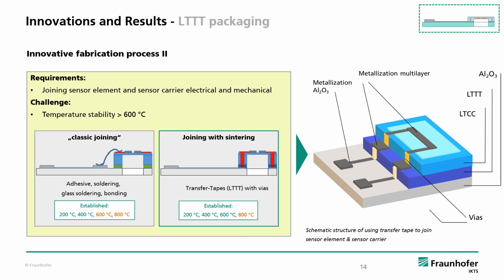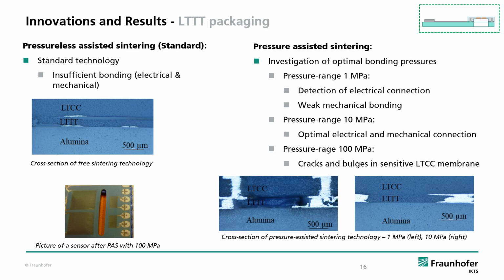The challenge in the LTTT process is finding the optimal sintering parameters. We started with the standard sintering process you can see on the left. Here we had an insufficient bonding, electrical and mechanical, as you can see in the cross-section. The other sintering technology uses a defined pressure while sintering, the so-called pressure-assisted sintering, you can see on the right. First of all, we had to investigate the optimal bonding pressures.